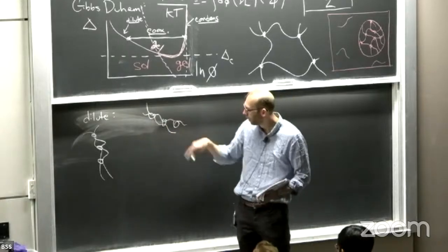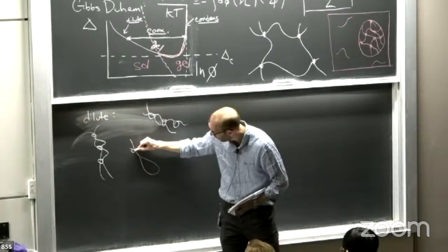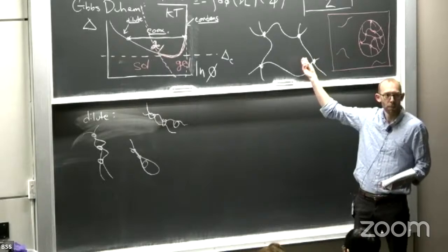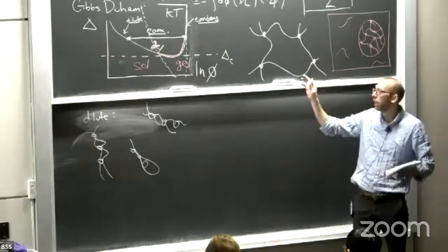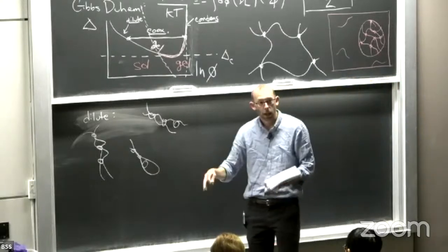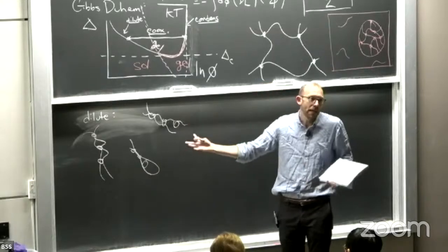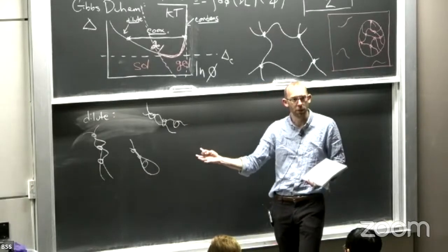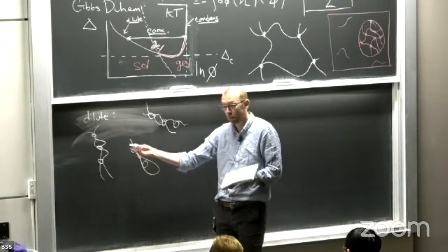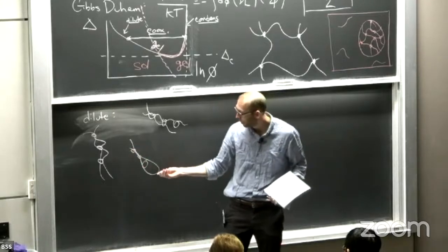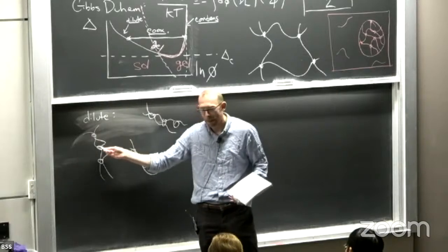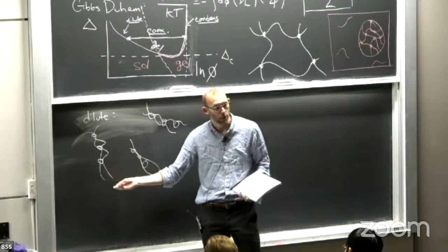Between, say, small dimers, or maybe something that's folded like this, where it can truly form intramolecular bonds, as opposed to having a system spanning network, because this costs a lot more entropically to bring many more polymer chains into close proximity. So this idea immediately violates our mean field assumption. To treat this, you can no longer say that the positions of our binding sites are uncorrelated in space, because we're saying precisely the opposite. If I find one associative bond here, I'm actually quite likely to find other ones nearby.